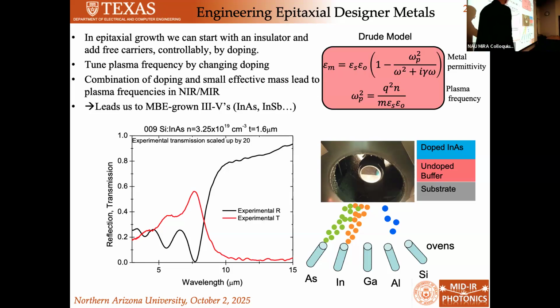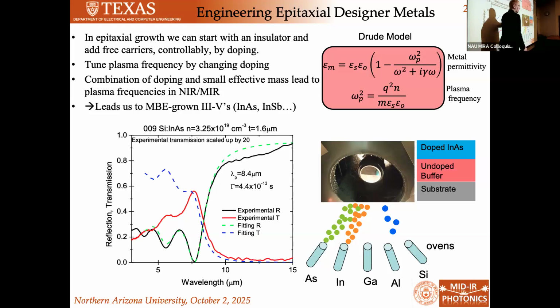what you see is rather distinct. You see these oscillations at shorter wavelengths. This is just Fabry-Perot modes of light bouncing around in this dielectric material. And then you see the sharp turn-on to high reflectivity. This is where your material becomes an optical metal. In fact, right around here would be the plasma wavelength. This is one of the very first samples that we grew. And if you model this simple three-layer stack with a transmission matrix method, and we use the Drude model to describe the indium arsenide, it actually gives us a pretty darn good fit.